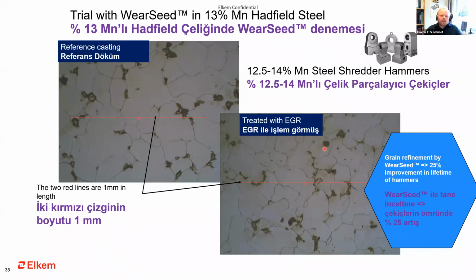So, usually for these manganese steels, the foundries are not really interested in mechanical properties because the end user is going to use them to crush rocks, and then all they're interested in is the actual lifetime of the components. And of course, smaller grain size should lead to better mechanical properties, which then should lead to a better lifetime for these components. But this was the first trial where we actually saw an increase in the lifetime.